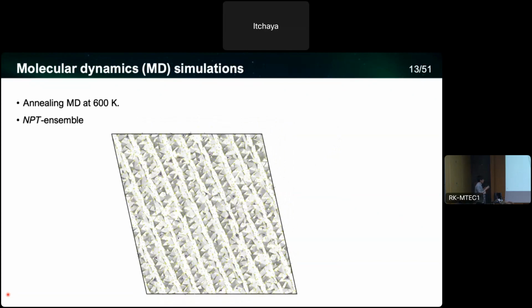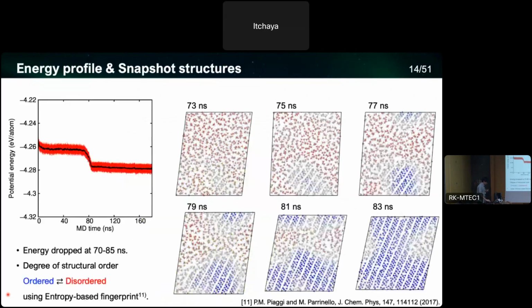So suddenly nucleation happens and it extends to the entire cell. The animation looks difficult for finding which part is crystallized, so we changed the way to visualize the snapshot. Anyway, here is the energy profile during the molecular dynamics simulations. As you can see, we have a sudden drop of the energy around 70 to 85 nanoseconds.